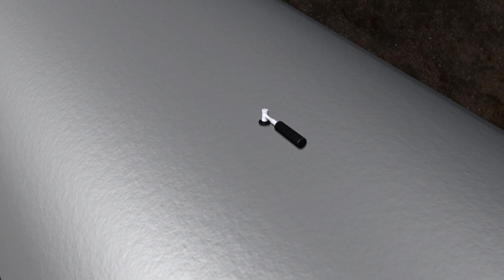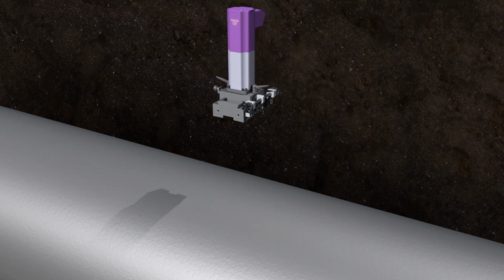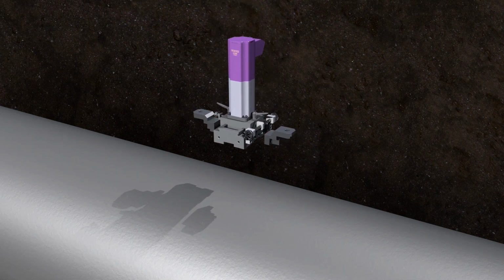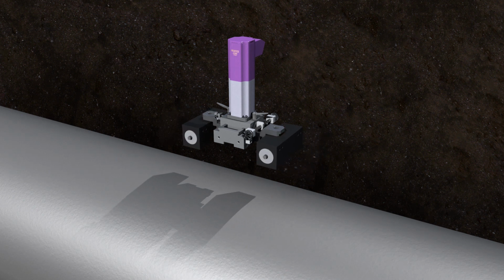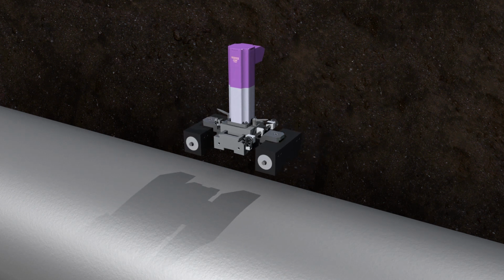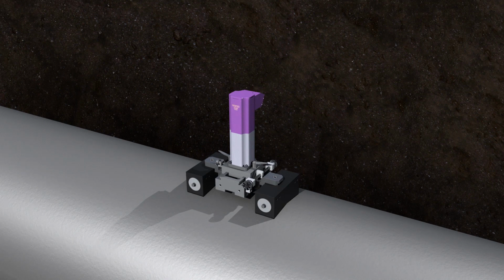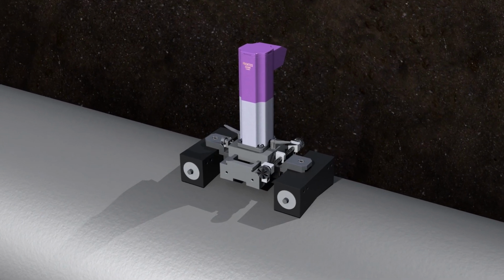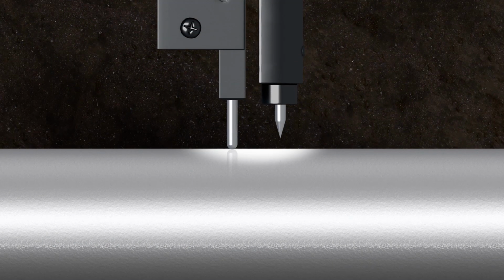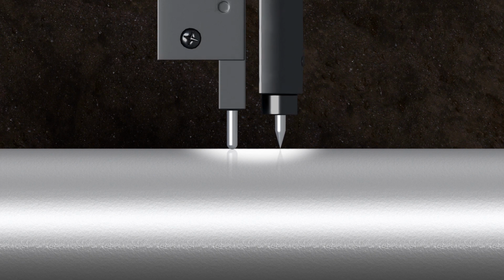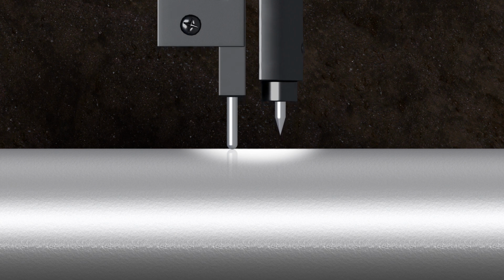Furthermore, it's applicable to diagnosing the pipe stress and determining the safety when relocating the pipe due to a development project in the vicinity. Test object is the main natural gas pipe connected to the gas governor station, and the test is intended to evaluate the pipe safety when deflection occurs by ground settlement. After surface profile is achieved, the tester is attached to the test object using the double curvature magnetic system.